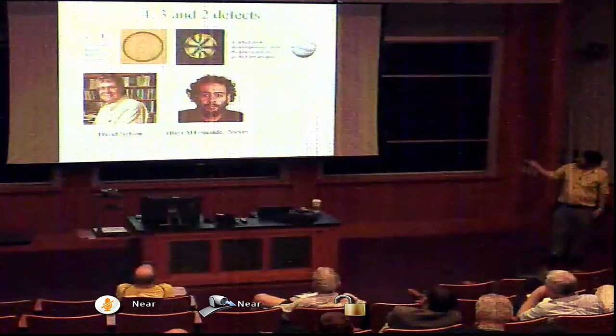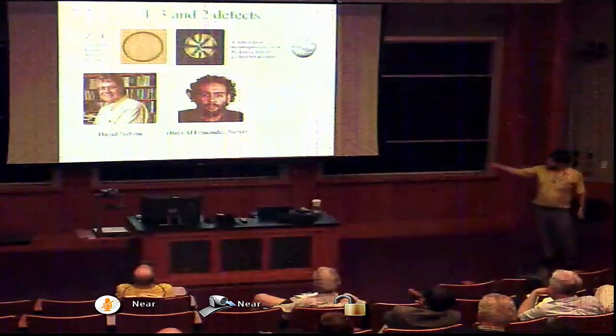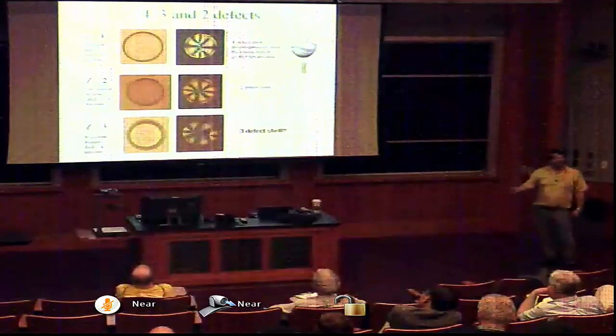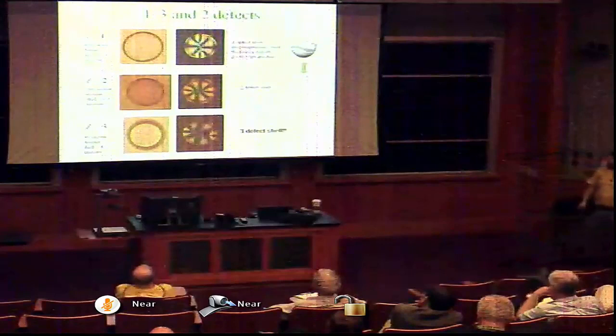These are these four defects, but rather than being symmetrically located, they're located all on the top because there's a difference in buoyancy. There was a little gravitational effect, and so the thickness of the shell changed. But when Alberto looked more closely, he sometimes found only two, and he sometimes found three. And so he had a lot of fun going back and forth with David to figure out what are all these defect structures with thin shells of nematics. And actually, it turns out that the thickness of the shell plays a big role in the structures that you get.